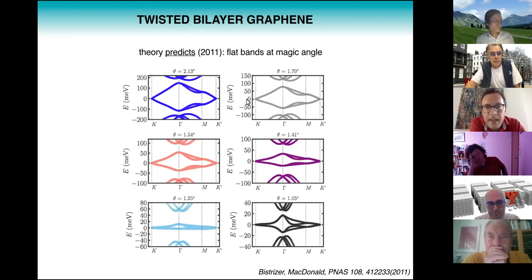So here I'm showing you again the evolution of the band structure. This is the non-interacting tight binding band structure as a function of twist angle. And what you see is that the width of these bands near the Fermi level shrinks and shrinks as you approach this magic angle. Here we're very close, and you can see these bands only have a width of maybe 10 millielectron volts. But then if you go beyond to even smaller twist angles, it opens up again. And of course, flat bands means slow electrons, and that means the electrons have very little kinetic energy. And that in turn means that it is likely that electron-electron interactions are going to play a prominent role in this material in the vicinity of the magic angle.